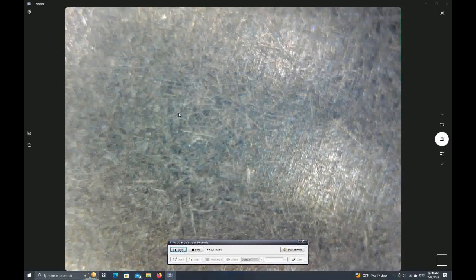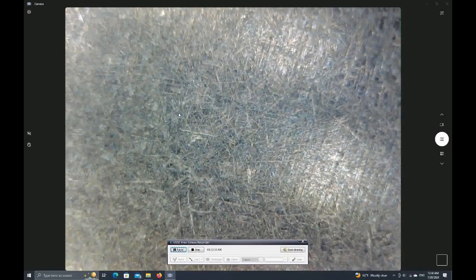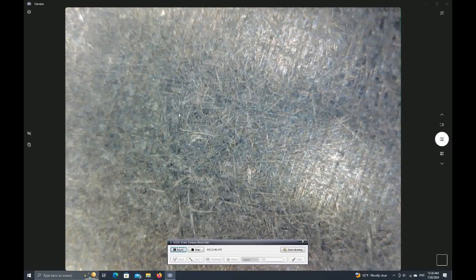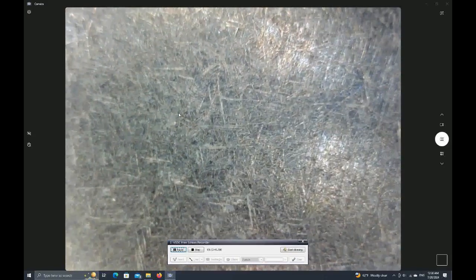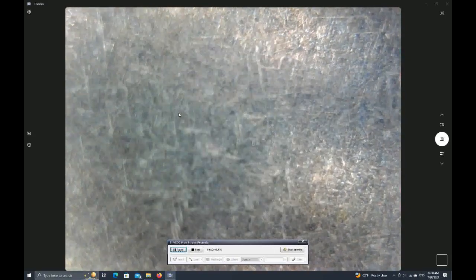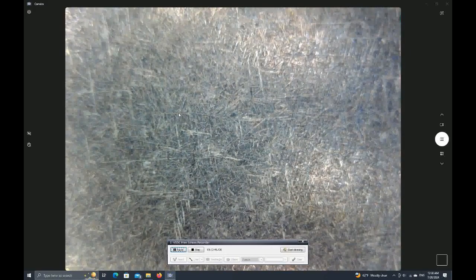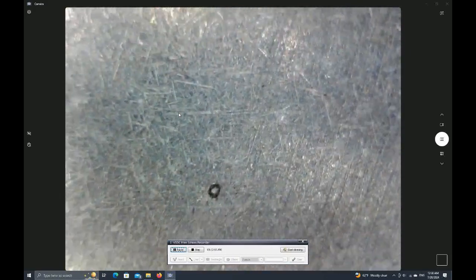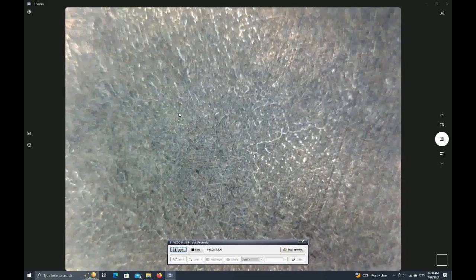That's good. And so we can see that even though we've got effectively the exact same metallurgical composition in terms of starting material added to the crucible, we have very different features because we had more of an oxidizing environment in this one, because we had the center portion of the ingot exposed to the ambient environment within the crucible. So I think ultimately we're going to have to treat these very differently when it comes to forging, but I would assume that we'll still be able to